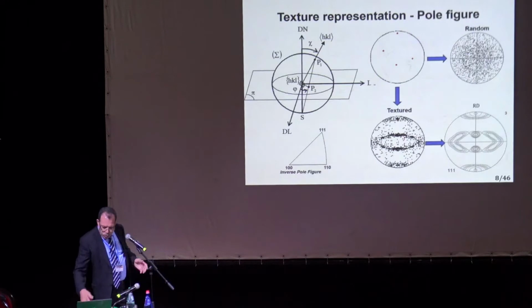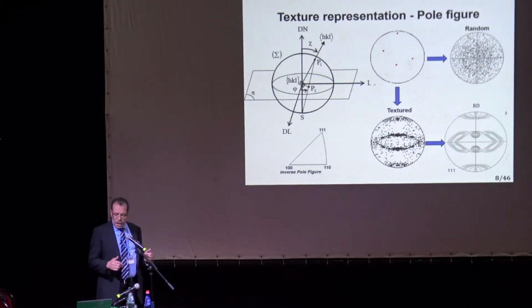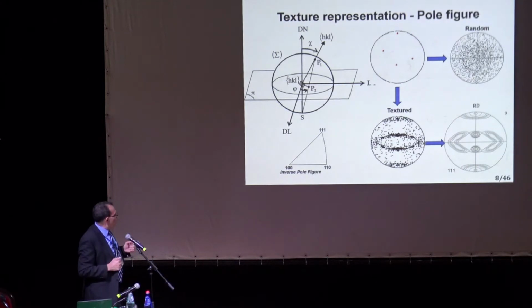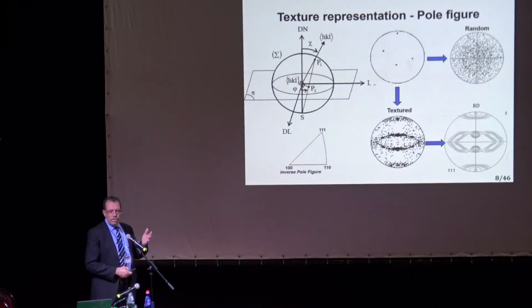But the easier way, or one of the easiest ways, is just to use the pole figures. Okay, either direct pole figures where you take a crystal, you plot the normal for a given crystallographic plane, and then you project it on the south pole, and when it intercepts the circle, which is the intersection with the plane that cuts the sphere into a half, that will give you a point. Okay, if you see on the top here, if I have a certain number of crystals, and each crystal will have, for example, if I have an FCC metal, I plot 111 planes, and I plot the normal to 111 planes, and if I see something like this in this pole figure, that means I have a random distribution. And in this, I have the macroscopic axes are here, 1, 2, and 3.